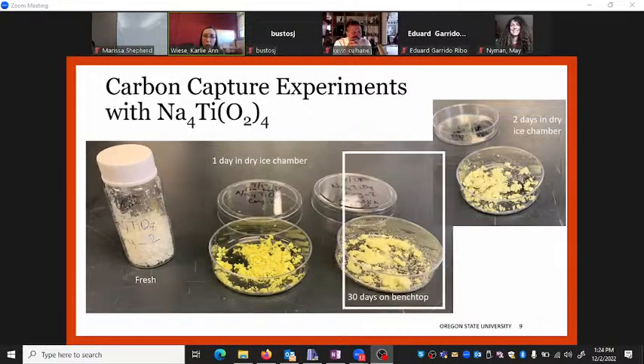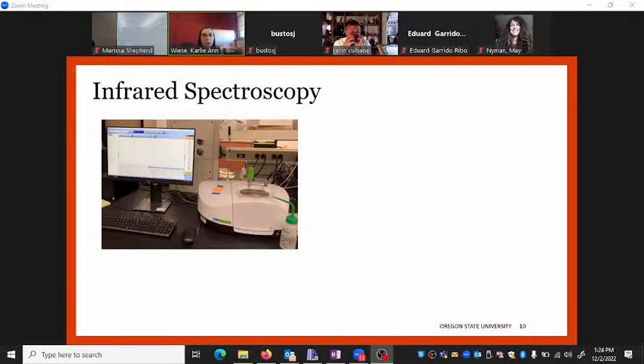And then we also put it on the benchtop just to see if we get a similar reaction with the CO2 in the atmosphere. It's much slower, but after 30 days, we also see that pale yellow color in the end. So something's definitely happening. That color change indicates something about our structure is changing. To learn a little bit more about what's changing in the structure, we have a few different techniques that we can use. One of them is infrared spectroscopy.